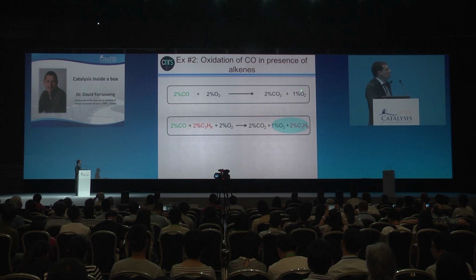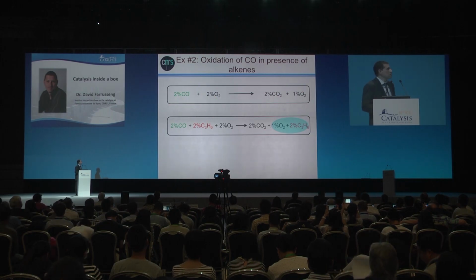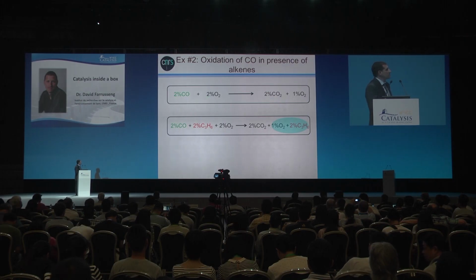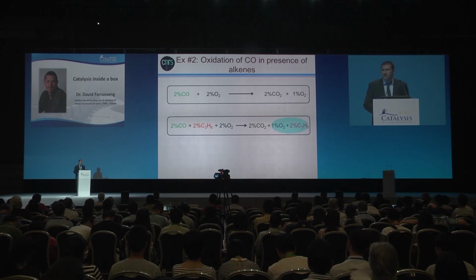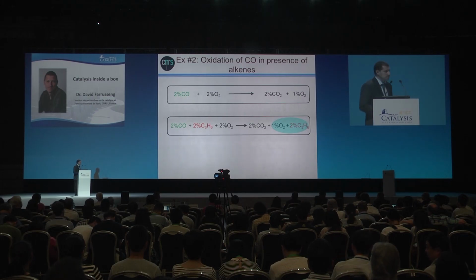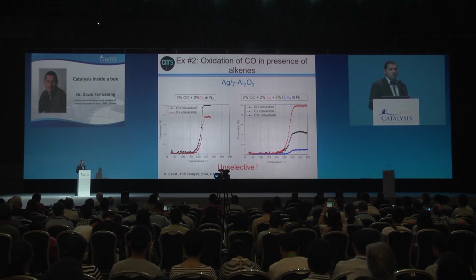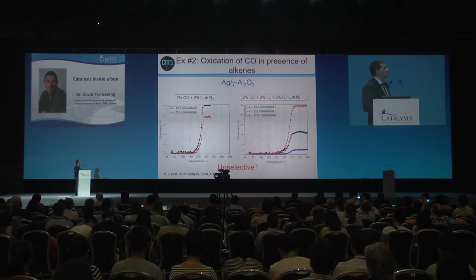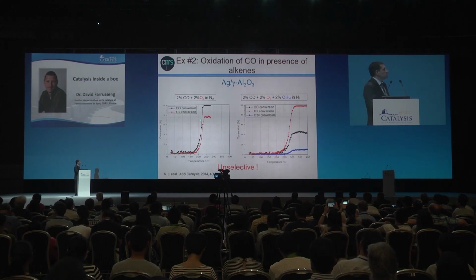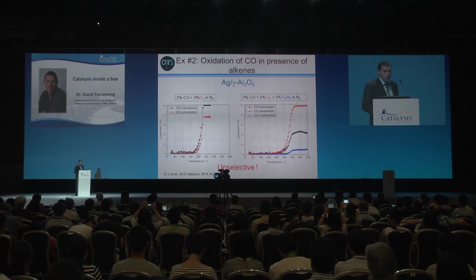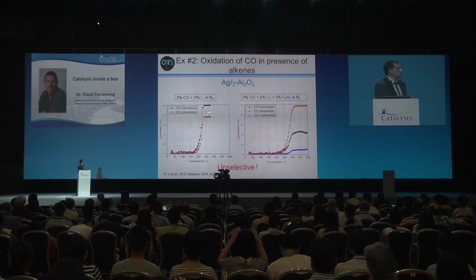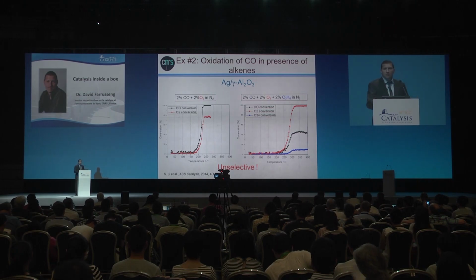So I will show you one reaction, the CO oxidation, very simple, with an excess of oxygen, and then we're going to add propylene, which will poison the surface of the catalyst and eventually also be burnt because of the remaining oxygen content. So here, as an example to show you how difficult it is to make these selective reactions, we have selected silver on gamma alumina. You can see here the conversion as a function of the temperature. Here in black is the CO conversion. You can see the light-off at about 200 degrees C. Very easy, oxygen conversion levels off at 70 because there is an excess of oxygen.